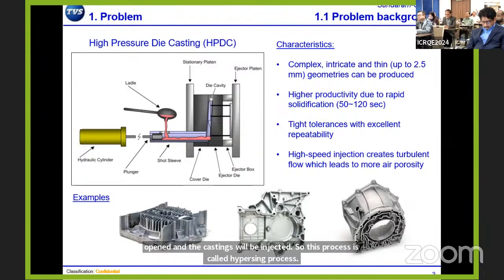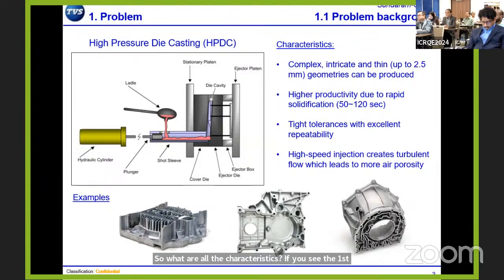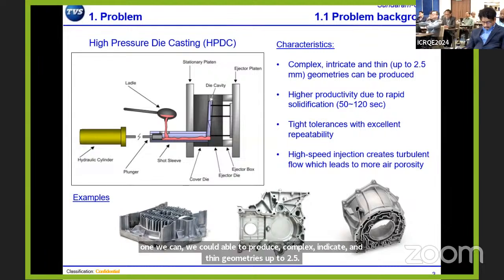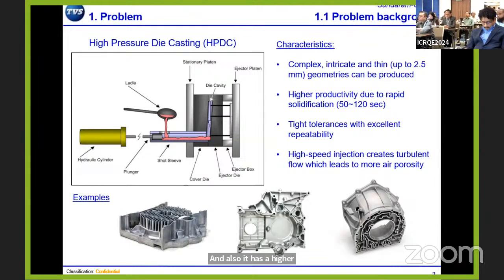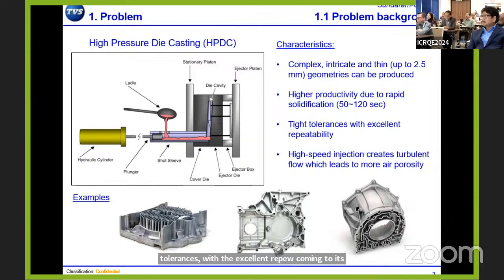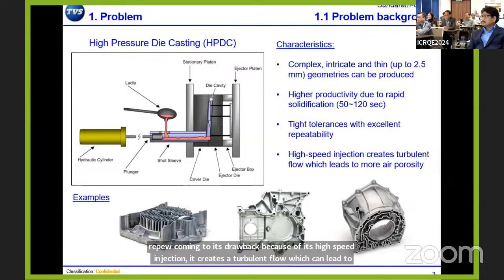So what are all the characteristics? If you see the first one, we are able to produce complex, intricate, and thin geometries up to 2.5 mm. It also has higher productivity due to its rapid solidification, so you could see the cycle time ranges between 50 to 120 seconds. And we are also able to produce components with tight tolerances with excellent repeatability. Coming to its drawback, because of its high speed injection, it creates a turbulent flow which can lead to more internal porosity. A few examples of the components made from this process.